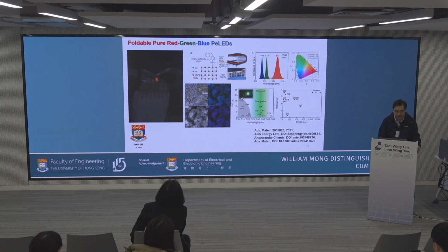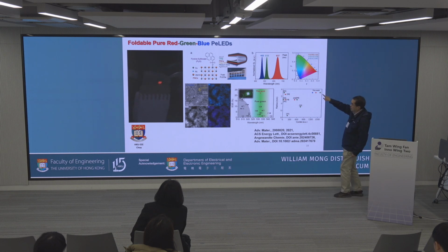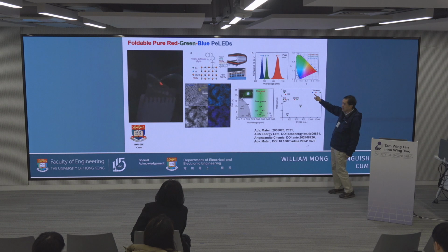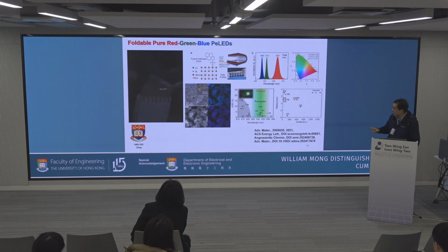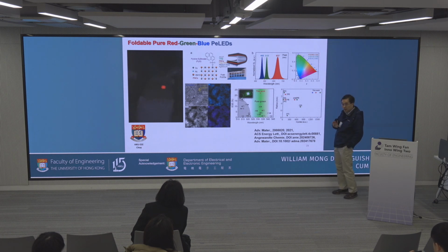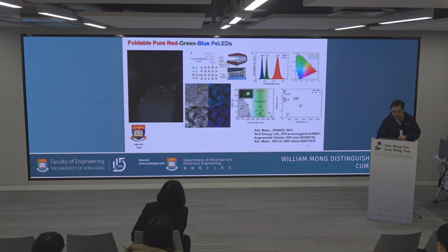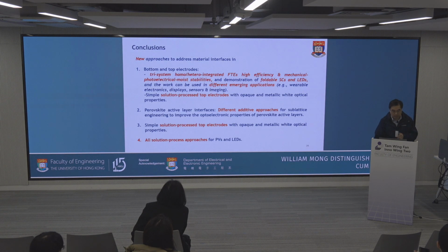Last but not least is the foldable LED. We use nanocrystals of perovskite. I don't have time to go through how we make the nanocrystals. We make pure red, pure blue, and pure green nanocrystals, and now we make a foldable LED with reasonably good performance. In terms of EQE, this blue one is about 10%, and the green one is about 28% EQE. The bending radius is 1 millimeter, and over 3,000 times it is still stable. Because of time, I guess I stop here.